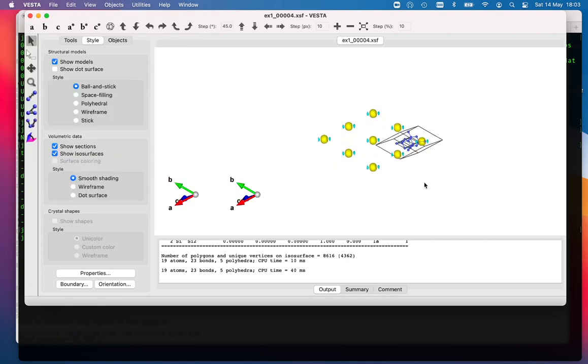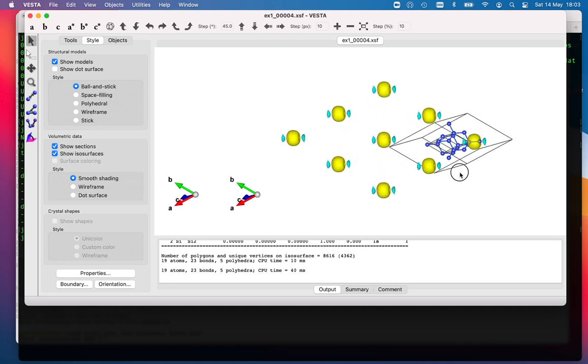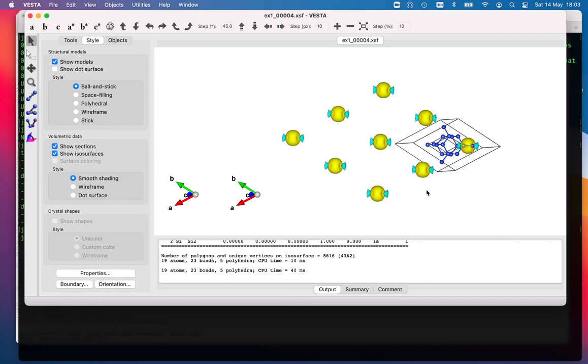I get this. Ooh. So the Wannier functions, as I said before, if we constructed them from an infinite sampling, a continuous integral of the Brillouin zone rather than a finite mesh of k points, then a single Wannier function would be isolated within the crystal. When we sample it with a finite mesh, however, they are periodic. Okay, so if I went and did a calculation on a 6 by 6 by 6 k-point grid, you would find that these Wannier functions would be further apart. If it was 8 by 8 by 8, this one wouldn't be here, and the nearest neighbor would be this one over here, for example. Okay, so it's just something to bear in mind when you're plotting, particularly if you've got very small k-point grids. Okay, and I think that's everything I wanted to show in this example.